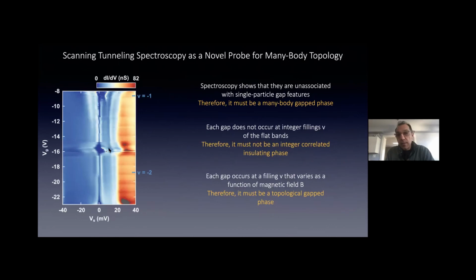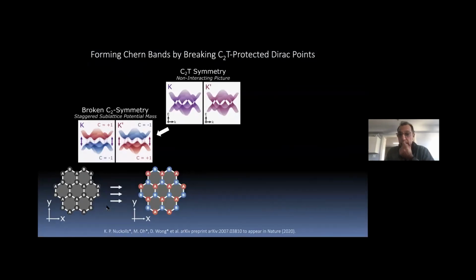If you observe a gap that is due to a single particle effect, it would not care whether your system is occupied or not. Here, the gaps associated with these Chern insulating phases of 1, 2, 3, corresponding to nu equals 1, 2, 3, the details of which don't matter to the non-expert, only occur at the chemical potential. So what this tells us is that what's giving rise to these topological phases is interaction between electrons, not some single particle physics like alignment with the BN, or even the Hofstadter physics, which would also give you other gaps in this material. So we are beginning to understand how these many body states are formed, together with Andre and other colleagues.